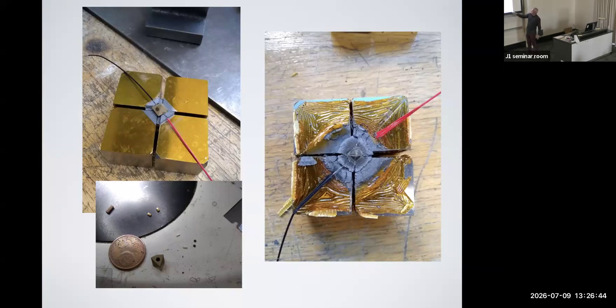So the interesting part is we measure temperature directly, right? This is also a challenge. We measure temperature directly in the center of the furnace assembly with the thermocouple wires. And of course, you can imagine, right, compression, and you have these very thin, hair-thin thermocouple wires. The whole thing is assembled under the microscope, centered here. If something is not quite aligned, then you break the thermocouple wire and you don't know what your temperature is, right? So this is what it looks like after the experiment, after it's been at 27 GPa and 2,200 kelvins.